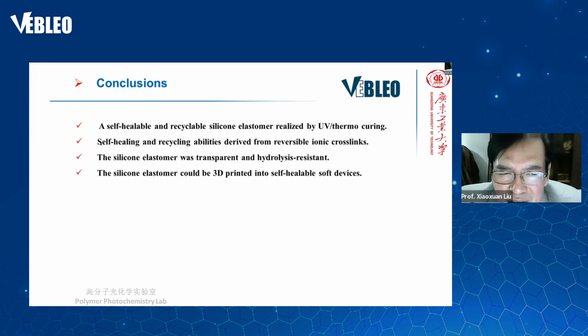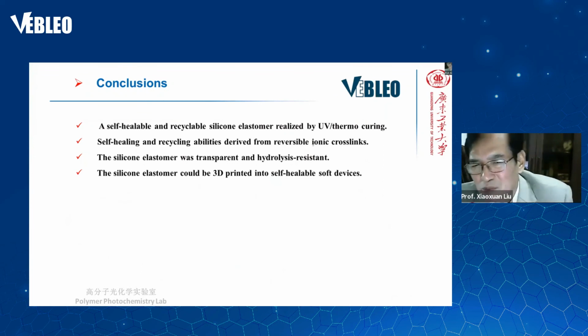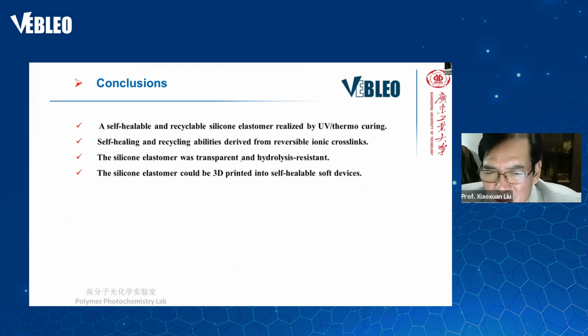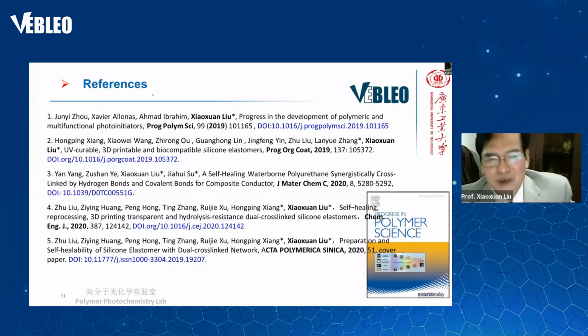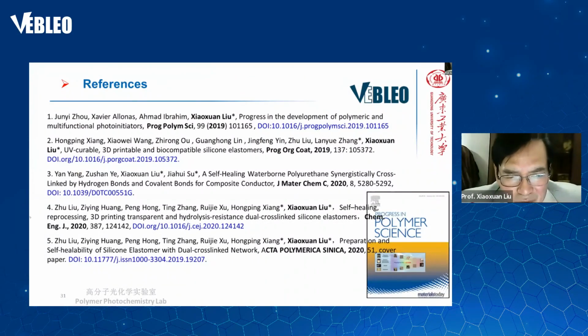So a conclusion: a self-healable and recyclable silicone elastomer realized by UV curing. The self-healing and recycling derive from reversible ionic crosslinking. And the silicone elastomer was transparent with hydrolysis resistance, and the silicone elastomer can be 3D printed into a self-healable soft device. So it is different, 1, 2, 3, 4, 5.